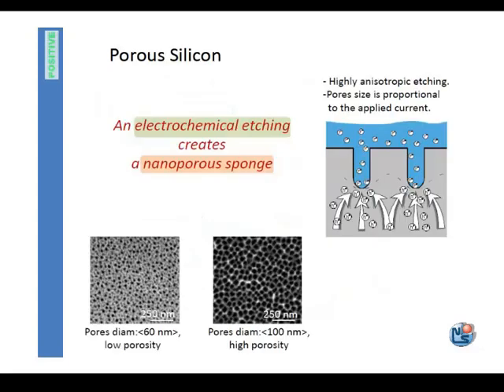So just a few words about porous silicon. Porous silicon is a type of nanostructured silicon that you can easily get from a silicon wafer. You place your silicon wafer in an electrochemical cell, you force a current or a voltage, depending on the condition, with hydrofluoric acid as etchant. At the end, you get this nanoporous sponge, where the pore size can be tuned over a very broad range, starting from a few nanometers only up to micron size.